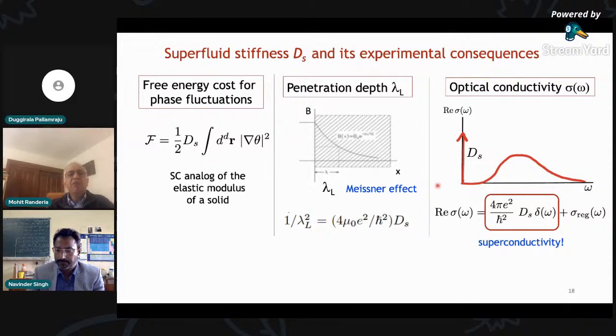Okay. Now you can say, how can I distinguish between a delta function and an infinite conductivity? The answer is there's a Kramers-Kronig relation. So there's an imaginary part. And the delta function will lead to a characteristic feature there, which can be measured in experiments and has been measured. So the strength of that delta function, the infinity, is actually the superfluid stiffness again, up to universal factors. So it is the superfluid stiffness which is related to both the Meissner effect and, in a sense, to superconductivity.